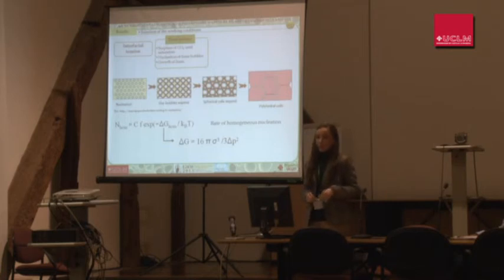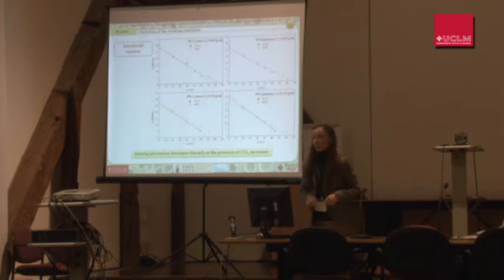To create a homogeneous microcellular foam, it's important to decrease the rate of homogeneous nucleation by means of a decrease in the Gibbs energy, and we can get this by lowering the interfacial tension. For this reason, we decided to measure it, and we observed that independently of the pressure, the temperature, the solvent, and the concentration used, interfacial tension decreases linearly as the pressure of CO2 increases.